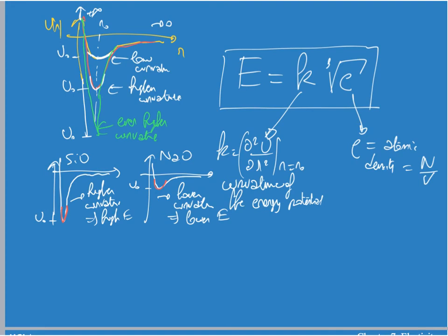So you see here that the Young's modulus has two main contributions. First, what is the stiffness of each individual bond? The stiffness will be higher for the bonds that are created by the network formers and will be lower for the bonds created by the network modifiers. So this tells you that the higher the bond energy, the higher will be the Young's modulus. The more network former you have with respect to the network modifier, the higher will be the Young's modulus. So the higher the connectivity of the glass, the fewer non-bridging oxygens you have, the higher will be the Young's modulus. So this captures the effect of the connectivity and the strength of the bonds.